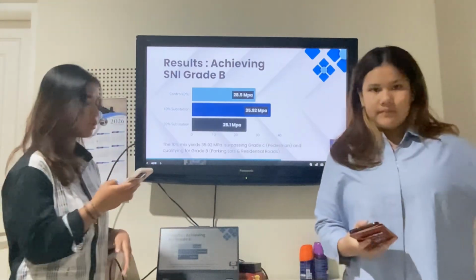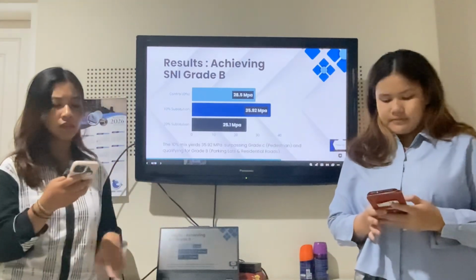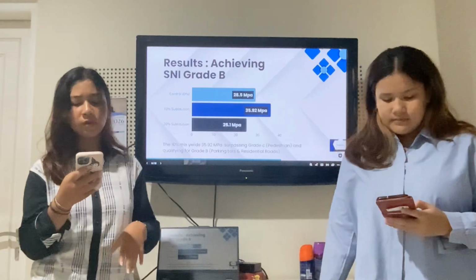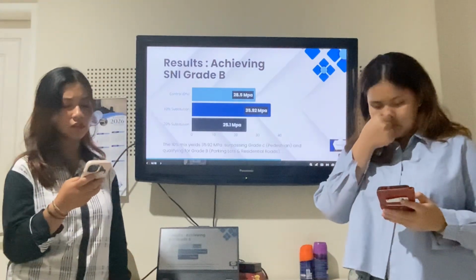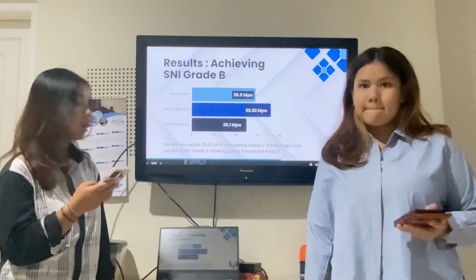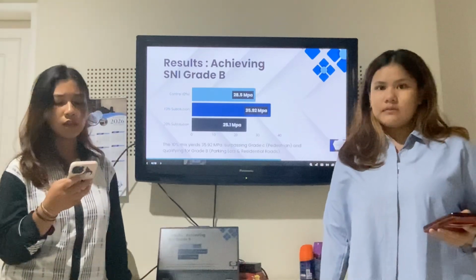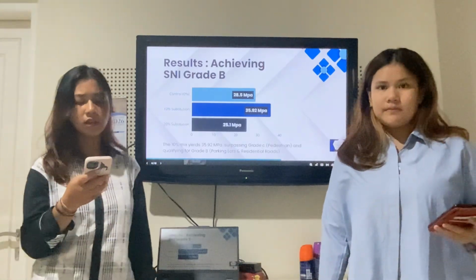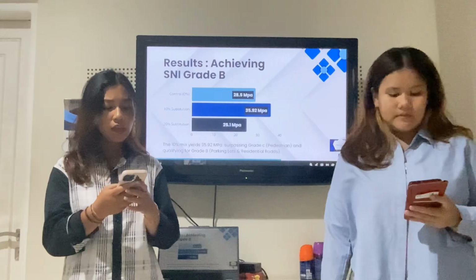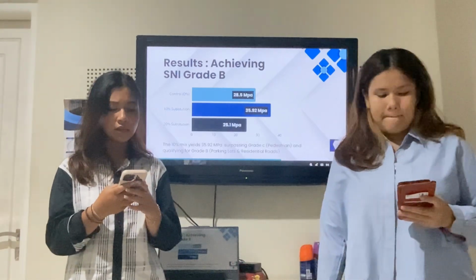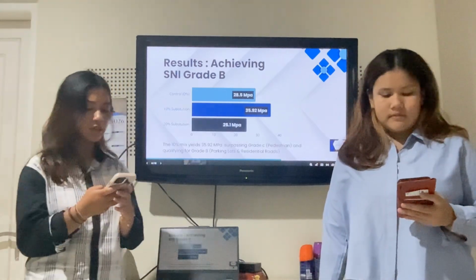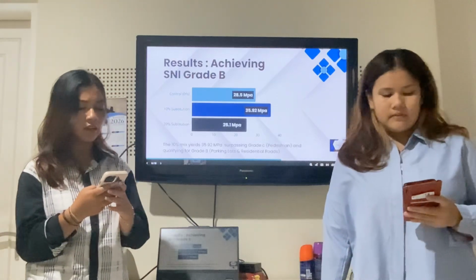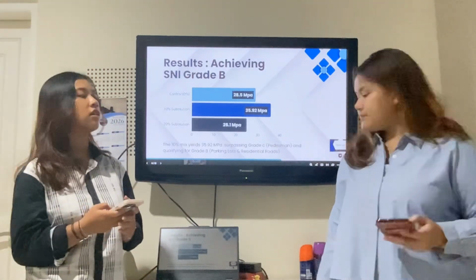As you can see on slide 8, the 10% substitution actually outperformed the baseline. It reached a compressive strength of 35.92 MPa. This is not just a fluke. It qualifies as SNI grade B, meaning it's strong enough for parking lots and residential roads.